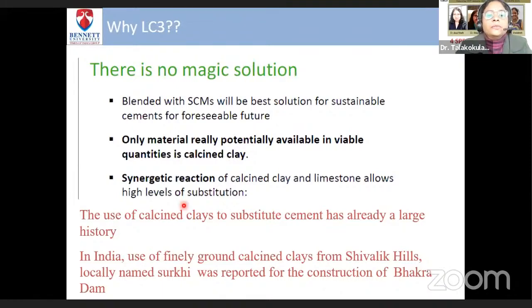And why clay? It's because of the synergistic reaction of calcined clay and the limestones, which allows us to use high substitution levels so as to reduce the content of cement considerably. This use of calcined clays to substitute the cement is not a new thing. It has a long history. If you look into our Bhakra Dam, they used finely ground calcined clays from the Shivalik Hills, commonly known as Surki, for the construction of Bhakra Dam. So the technology is not new.